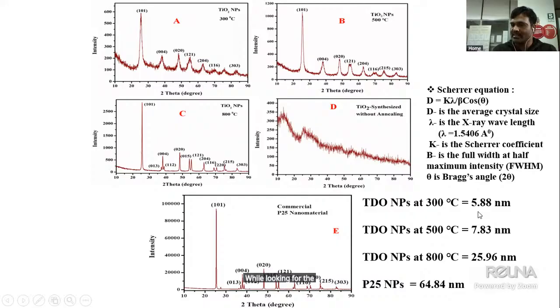Here the crystalline size of the material is calculated by the Scherrer equation, the Debye-Scherrer equation. Looking at 300, it is less than 5 nanometer. At 500, the titanium dioxide is less than 10 nanometer. While looking at 800 degrees, 25 nanometer is confirmed as the crystalline size by the Debye-Scherrer equation.